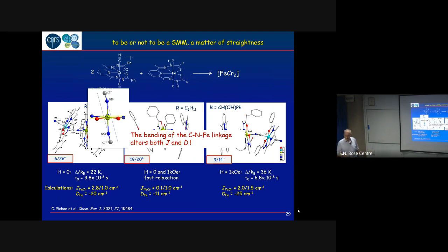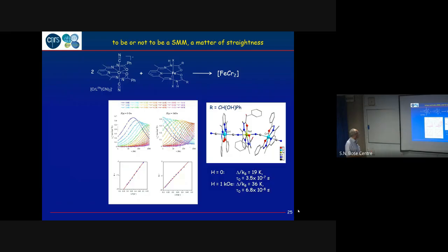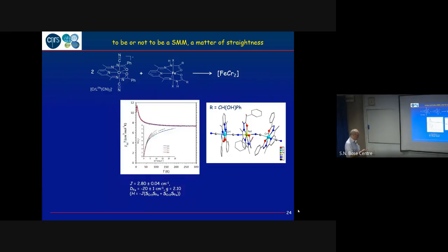Just related to the chi T versus temperature curve, do you have the magnetization curve? Yes. So how does it look? M versus H. We have something that is almost linear. You don't observe any hysteresis in there. Not at this temperature. You will see later I have some. But here, for this species, we should go below 2 K. Okay. We are still at too high a temperature.